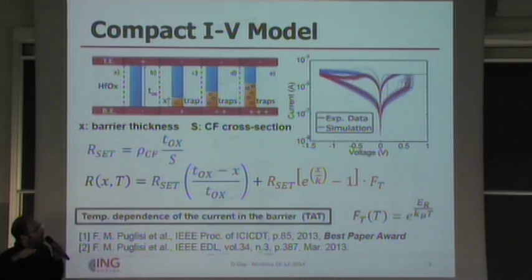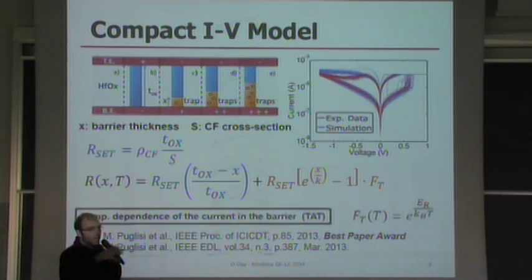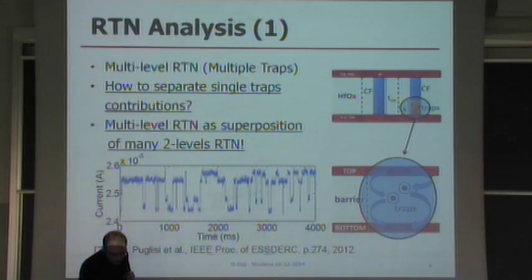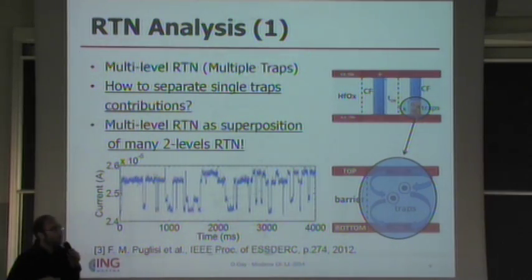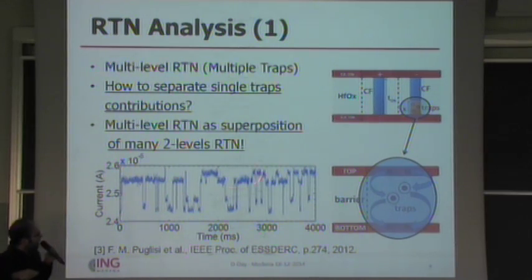So by looking at the IV curve, a very simple experiment, we can extrapolate the cross-section and eventually, when we are in high resistive state, the thickness of the dielectric barrier. So we can relate electrical and physical characteristics. But I also told you that we are dealing with a read disturb. It's called random telegraph noise, and it looks like this.